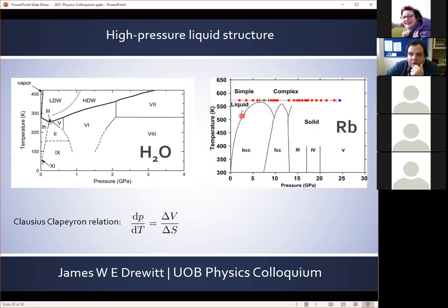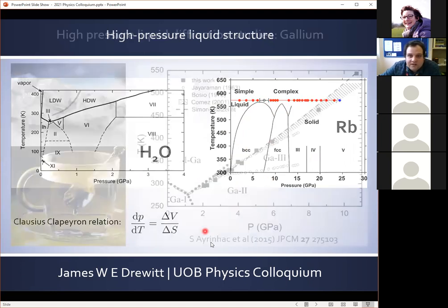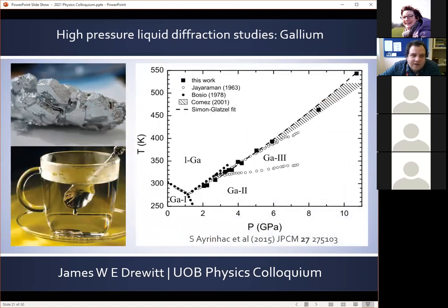So similarly for rubidium, we see the simple to complex structure transformation coincides with a maximum in the rubidium melting curve. And in fact, rubidium undergoes several maxima and minima in its melting curve behavior, coinciding with polymorphic transformations taking place in the crystalline solid state. So I'm going to focus on some measurements which we made at high pressure on liquid gallium.